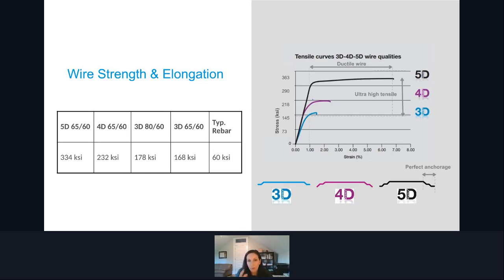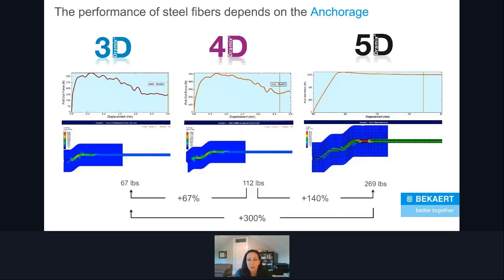If you'll notice in the graph on the right here that the 5D fiber at the top also has a significant elongation capacity, up to about 6% elongation. That's where the ductility of your SFRC with 5D fibers would come from. And that plays right into this next section, which is a discussion on the anchorage of the fibers. So knowing how something fails is an integral part of knowing how to design with it. So 3D and 4D fibers both have a similar failure mechanism. It's a controlled pull out.